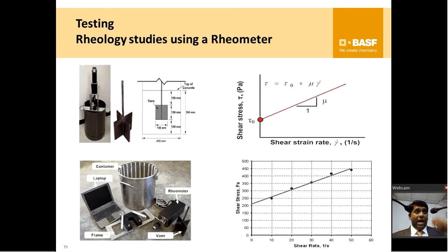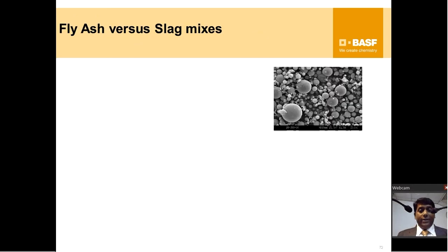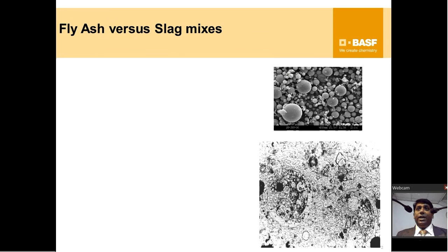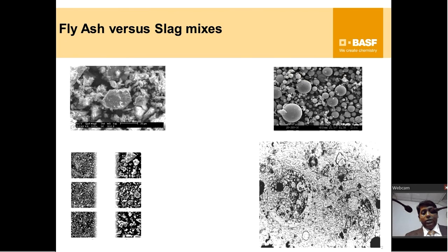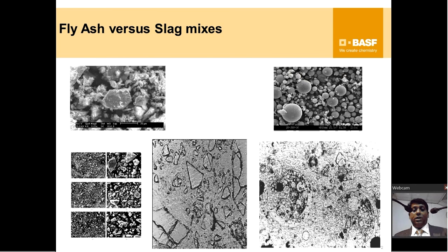So some lab and field testing, a lot of rheology testing, was done. If you want to pump the concrete up to 600 meters high, a lot of rheology tests need to be done in terms of shear stress, plastic viscosity, and so on, and then we finalized the product. This is what a rheometer typically looks like. We tried various supplementary cementing materials, whether to go with a fly ash mix or a slag mix. Finally, we went in with a fly ash mix.